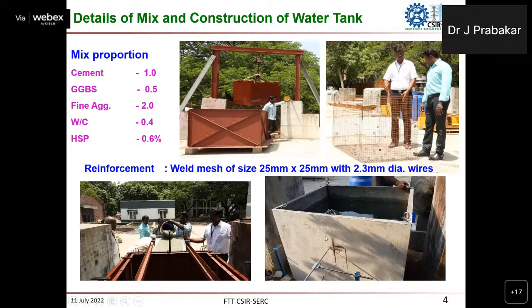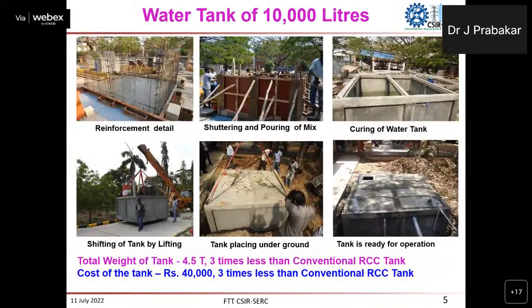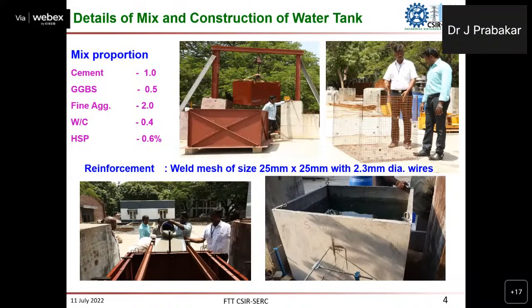All properties, like deformation, stress and strain, were measured by filling the tank with water, full water. We can even lift the water tank through these four corners. At the time of construction itself, we have fixed these hooks. Through these hooks, we completely lifted the water tank, and we also measured the deformation, and all the measurements from the structural point of view have been carried out.